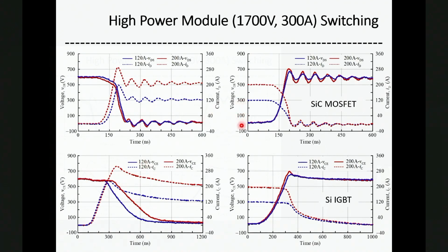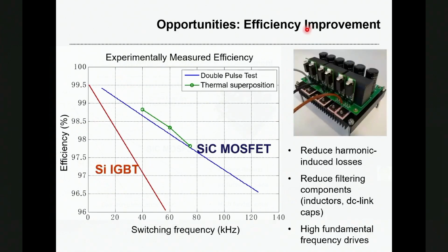This slide shows the experimental test for high power modules, both the silicon carbide MOSFET modules and the silicon IGBT modules. As you can see, the silicon carbide MOSFET can turn on and turn off very fast, generally within 70 nanoseconds, but the silicon IGBT has a much longer turn on and turn off time, and you can also see the clear tail current during the turn off. These are the tests for the 1700 volt, 300 amp modules.